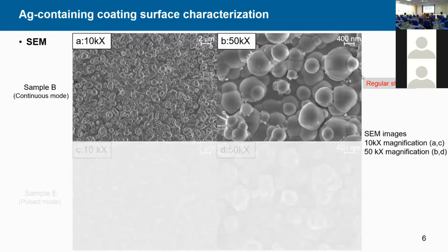When we use water aerosol to replace silver nitrate aerosol for sample F, the coating surface is almost uniform with slight defects. Normally, plasma polymerized HMDSO coatings are flat, and the defects can be caused by filaments forming in the discharge due to the presence of water aerosols, leading to local strong fragmentation and